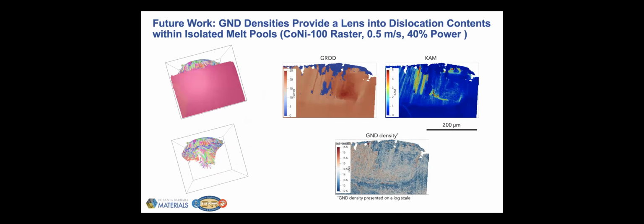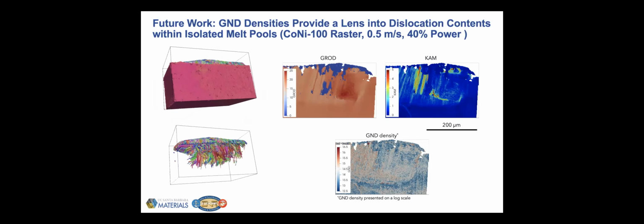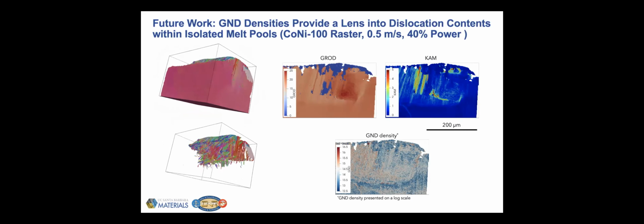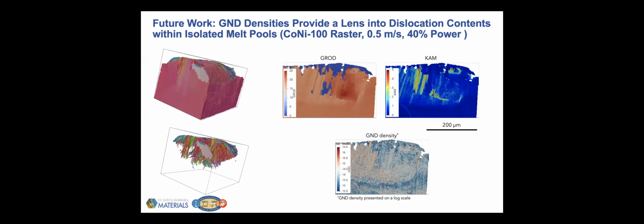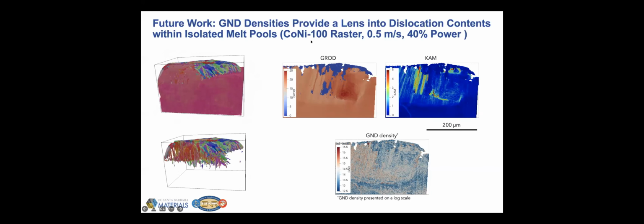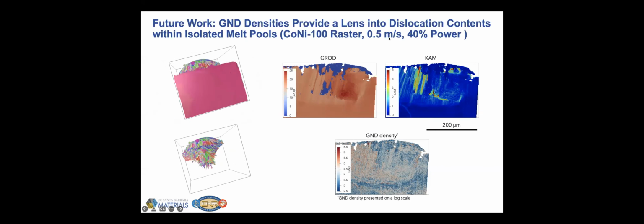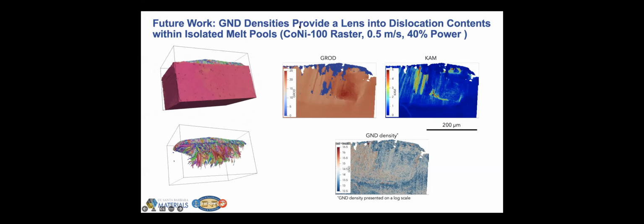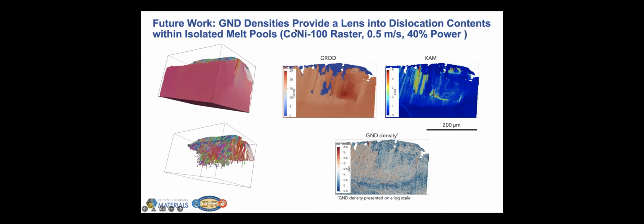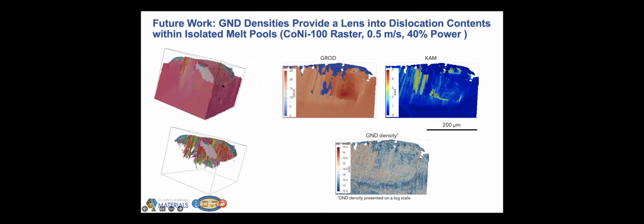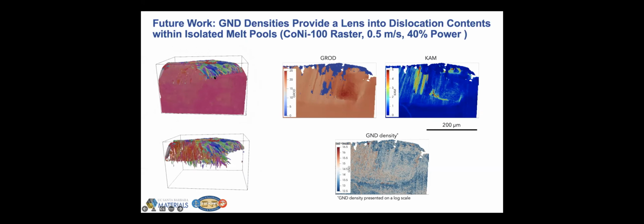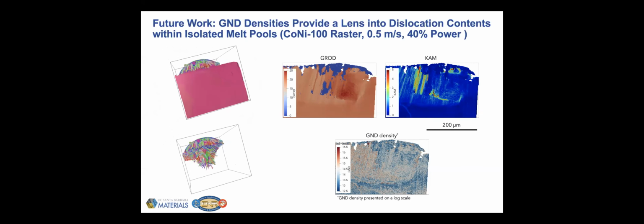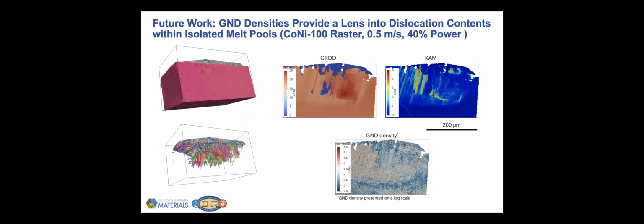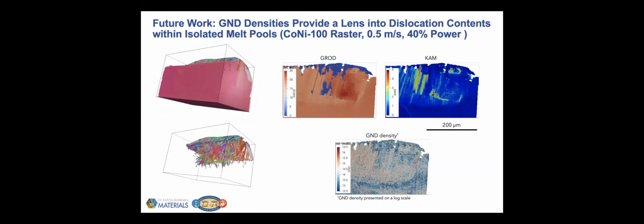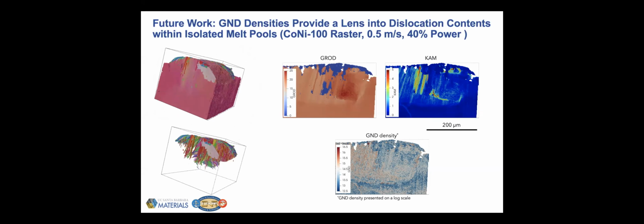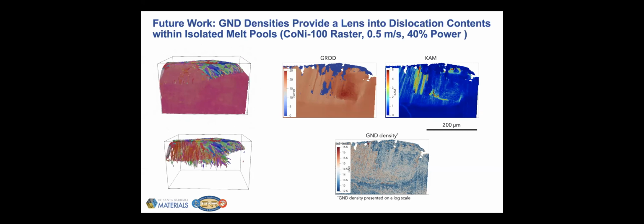Another thing we can get from the tri-beam, for example, are geometrically necessary dislocation densities that tell us about the local dislocation contents. This is an example from the UCSB group where we did some APS experiments with them as well on a cobalt nickel alloy, designed for AM. And here we can see again, nice 3D representation of all these grains. And then this will be coupled back to the synchrotron work that we're doing and also the modeling as well. And we can really start understanding a lot about what's driving the microstructure evolution during additive manufacturing.